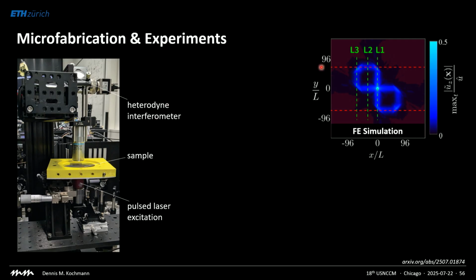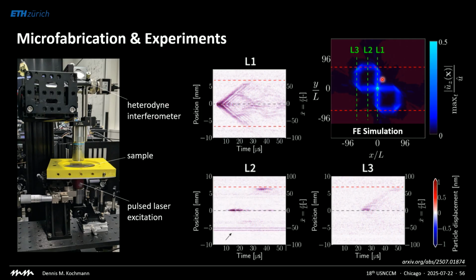And if this is the figure 8 that we simulated in the beginning, we can now do line scans. If you go around along line L1, you'll see that the wave spreads exactly until it hits this point up here, and then the wave disappears because it turns by 90 degrees. If you go along line L2, you'll figure out that nothing happens until the first wave hits here, and then the second one hits there. At L3, you see the wave arrive after a while and then keep going.